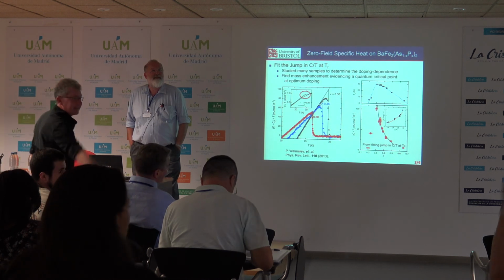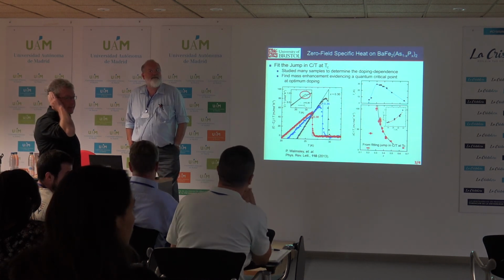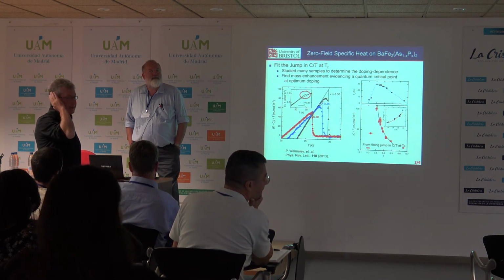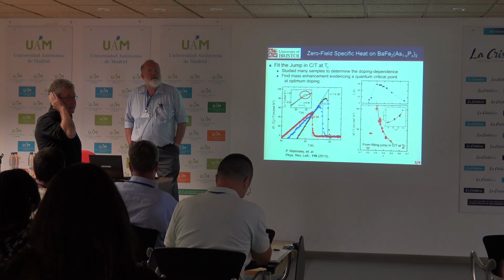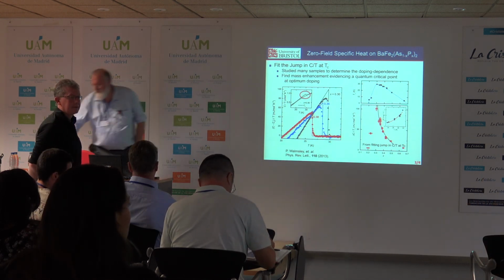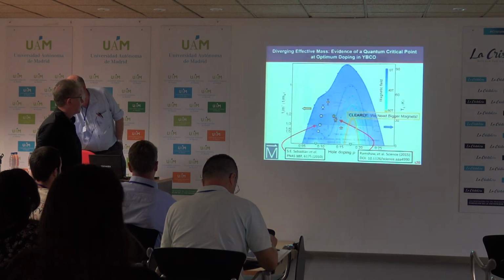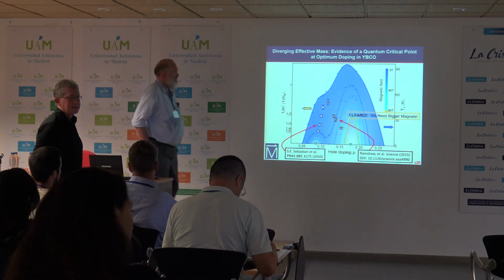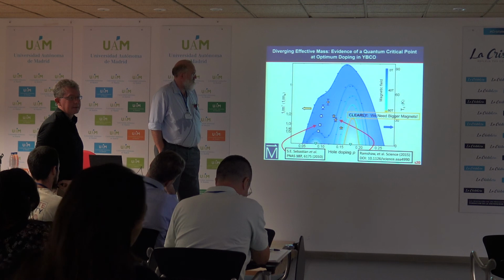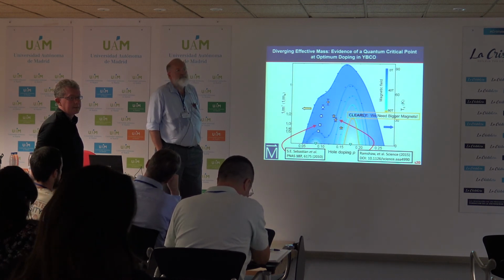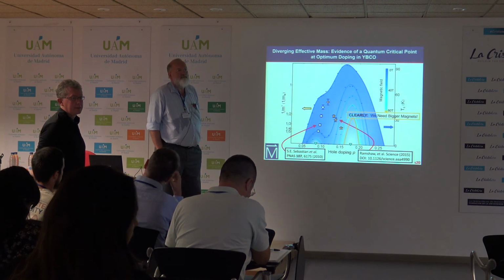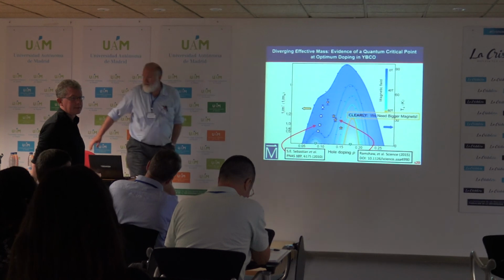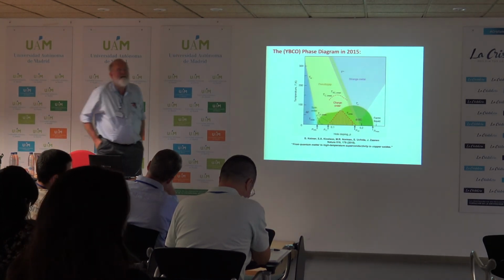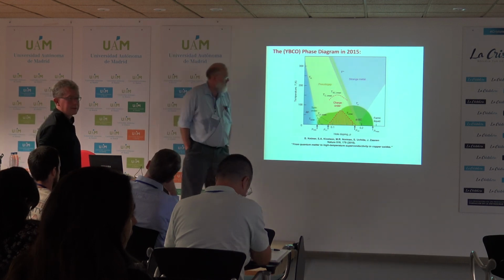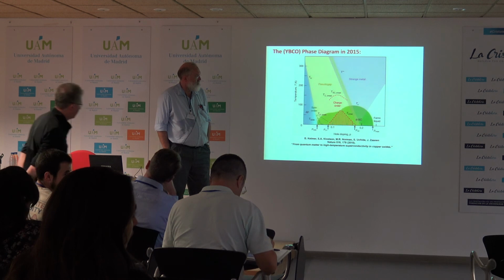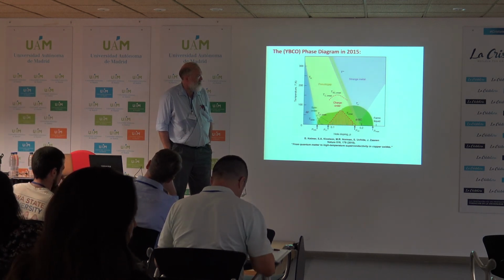Yeah. All right, Tony. Greg, switching back to the cuprates, you emphasise that there's an increase in the mass at two points in the dome. For the one near optimal doping, if you wish to interpret in terms of coupling to critical fluctuations, there's two possible orders you're coupling to: the pseudo-gap or the CDW. But on the one on the left, the only game in town is the CDW, right? So isn't it then logical to say that the thing which is giving you mass enhancement on both of these is indeed the CDW, and that neither of them have got anything to do with high temperature superconductivity?